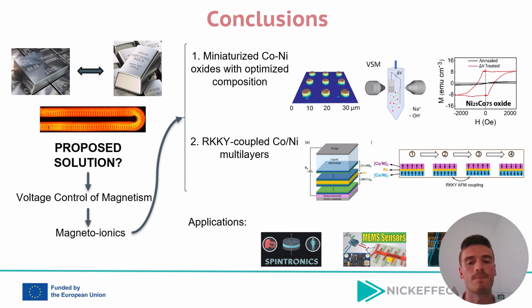In practical terms, we first developed miniaturized cobalt-nickel oxide with finely tuned compositions, which showed promising magnetic performance as demonstrated through techniques like vibrating sample magnetometry. In particular, we can see how applying a voltage can significantly change the magnetization behavior of samples like nickel 25 cobalt 75 oxide, proving that voltage controlled magnetism is feasible in this kind of system.